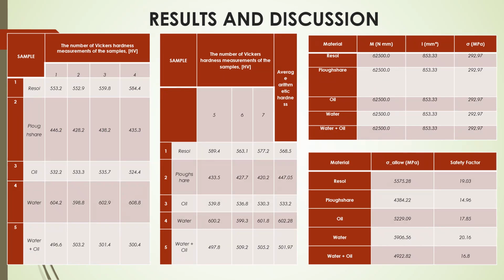In this section, our hardness test showed that untreated plowshare had the lowest hardness, around 447 HV, while water-treated samples reached about 602 HV. Especially if we consider the safety factor, untreated plowshare was only 14.96, but with water quenching it increased to 20.16, the best result among all treatments, I think. In summary, I can see that water heat treatment proved most effective, giving plowshare higher hardness, durability, and reliability for agricultural use.